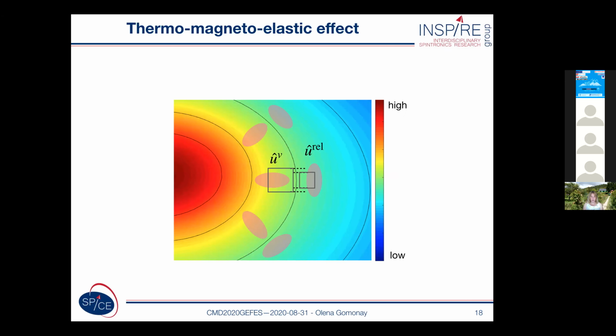It is an exaggerated picture of the inhomogeneous temperature distribution in the antiferromagnetic layer. The temperature induces a volume effect, volume expansion, but this volume expansion is larger in the hot regions and smaller in the cold regions, as you can see from the squares in this figure. And this different lattice expansion does not fit together at the interface between cold and hot regions. And it can break the continuity of strains or lattice of the sample.